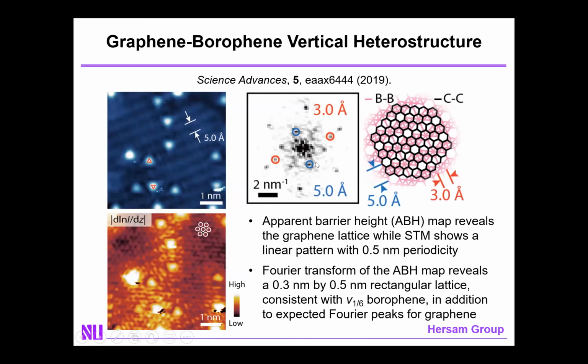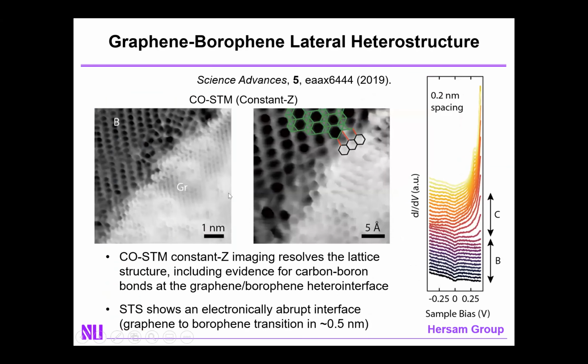If you then zoom in and look at particular cases, such as the graphene-borophene vertical heterostructure, you learn that based upon the imaging conditions, you can either reveal the graphene lattice, which is clearly apparent in apparent barrier height imaging, whereas if you tune into other imaging modes, such as more conventional STM imaging, you can reveal the borophene lattice. And because you can get these images in the same region, you can use methods like fast Fourier transform analysis to determine the relative orientation of those two layers in the vertical heterostructure.